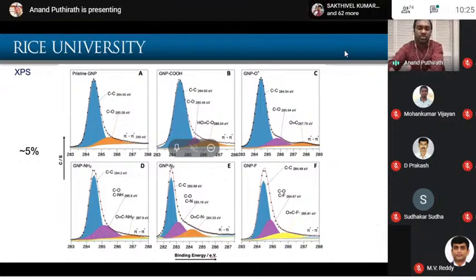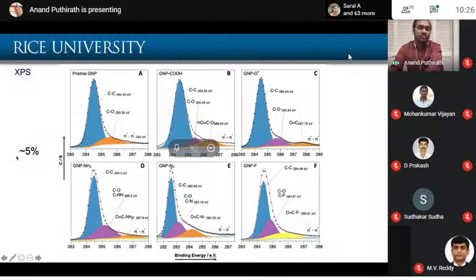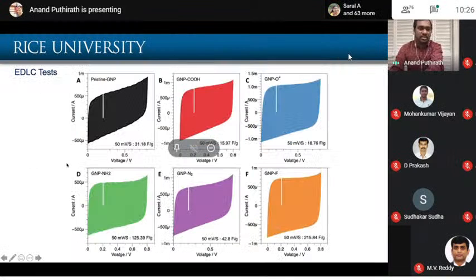And through XPS, you can actually quantify how much functionalization you brought into the system, from the area under the curve for each different bonding type. You can actually quantify how much your functionalization is relative to the bulk structure. You will have carbon more, and how much functionalization you bring can be deduced from XPS.